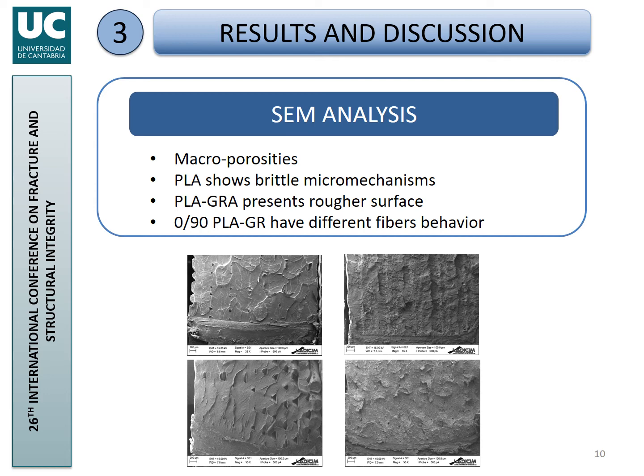However, if we focus our attention on these two images here, this corresponds to the 0/90 raster orientation of pure PLA, which is brittle, and this corresponds to the 0/90 raster orientation with 1% of graphene. It may be observed that there is a change of fracture mechanisms just in one half of the ligaments, those corresponding to a particular orientation, with the other orientation having still brittle mechanisms.